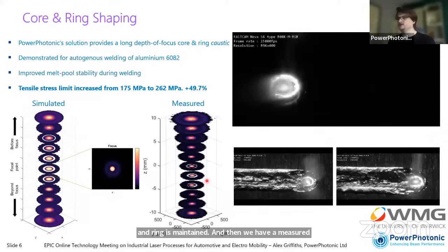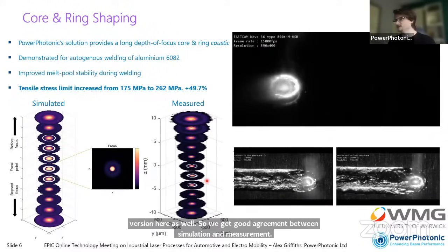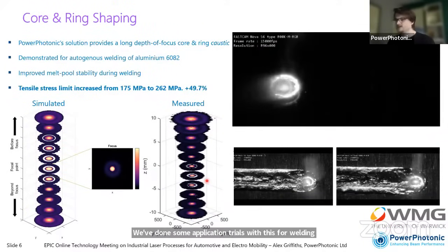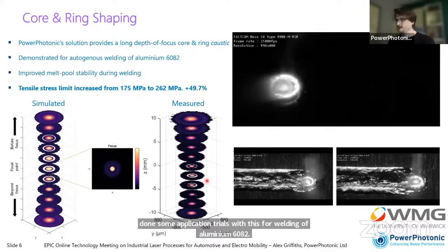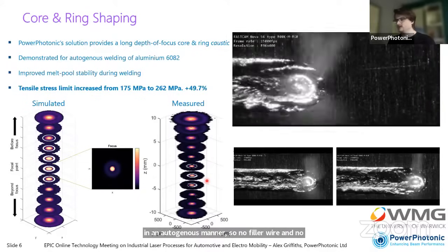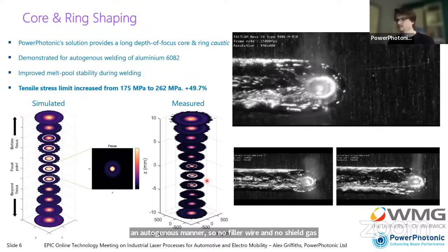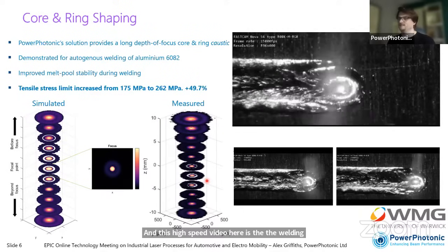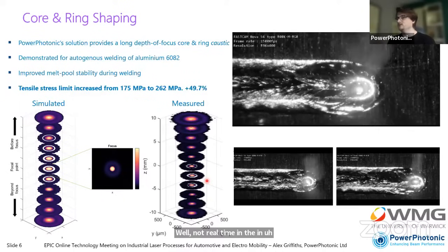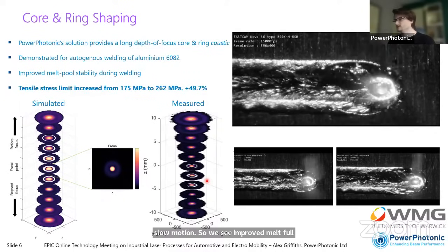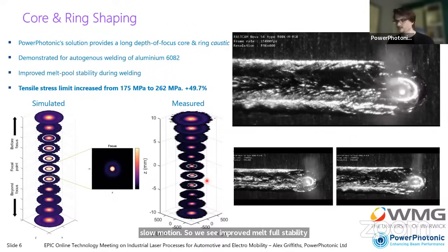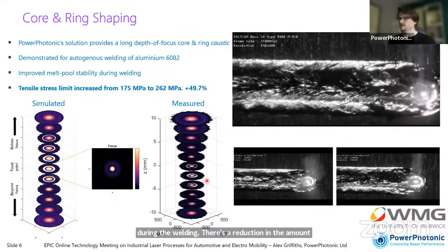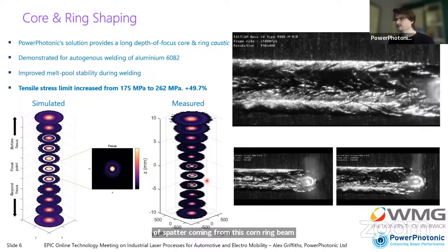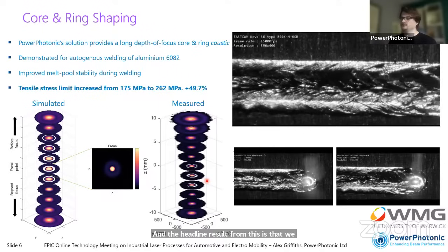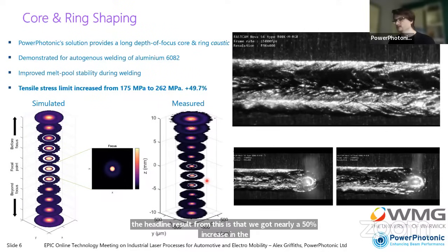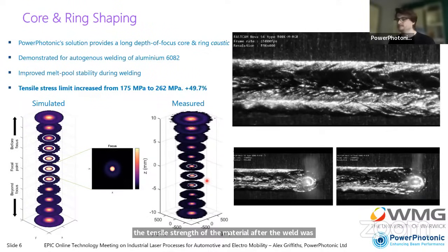We've done some application trials with this for welding of aluminium 6082 in an autogenous manner, so no filler wire and no shield gas. And this high-speed video here is the welding, not real time, in slow motion. So we see improved melt pool stability during the welding. There's a reduction in the amount of spatter coming from this core and ring beam. And the headline result from this is that we got nearly a 50% increase in the tensile strength of the material after the weld was done compared to welding with no beam shaper.